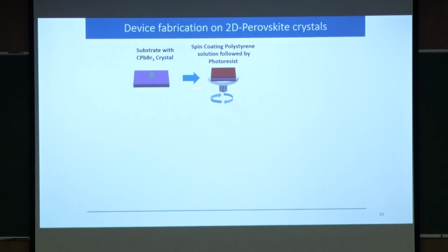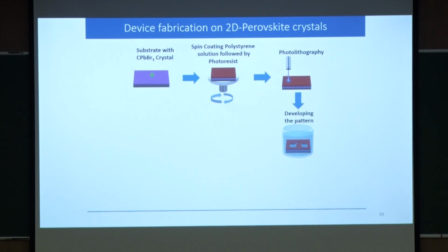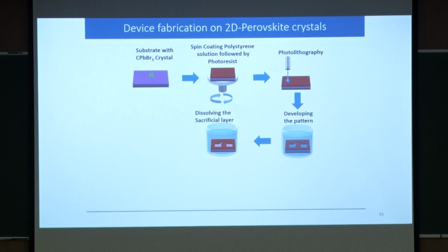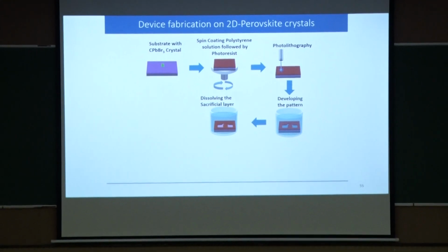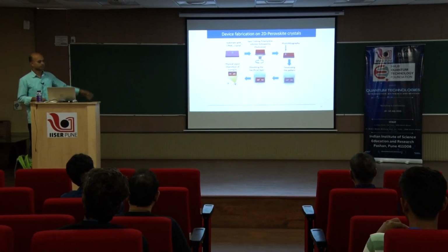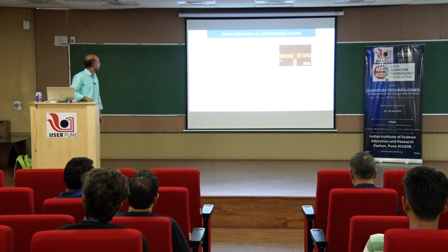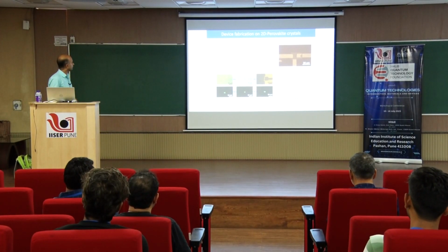So, what we do, we deposit polystyrene, and then we deposit photoresist on top of it and do the conventional lithography. We develop it in the water based developer, because polystyrene is protecting the sample. Once that is done, then we dissolve the sacrificial layer. Here it is toluene, so no water is there. We get the pattern, and then we deposit metal, and finally we do the lift off, we get the device. We are successful in making devices.